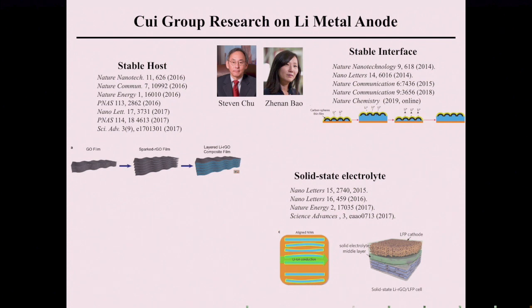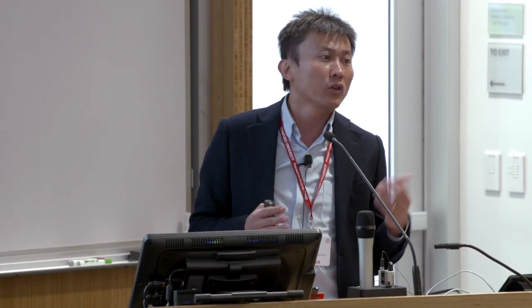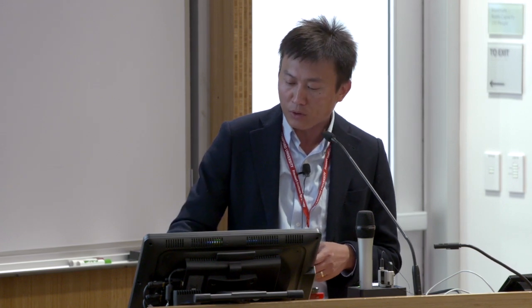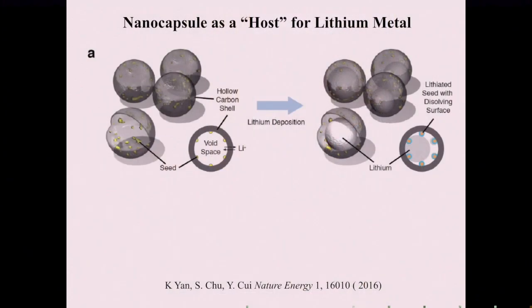So let me just give you one or two very simple ideas, but they actually turn out to be very important for the whole research field. Because lithium metal can grow this dendritic structure, how do you really control its plating behavior during battery charging? In 2016, we came up with an idea. We said, let's design a host material to host lithium plating. We made a hollow carbon structure, with a diameter of about a few hundred nanometers, with gold nanoparticle seeds in there. It doesn't need to be gold. It can be other low-cost metals seeding the growth of metallic lithium.